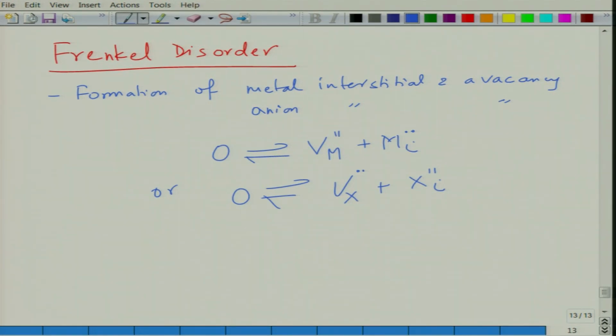In both cases, either this or that, the stoichiometry is not disturbed because metal has not gone out of the system, it has remained inside the system. So M to X is the same, it is preserved. Okay. So mass is preserved. You can see there is site preservation. You have not created any extra site because it has gone to an interstitial site. Interstitial sites cannot be created or destroyed. And a vacancy has been created on the metal site itself.